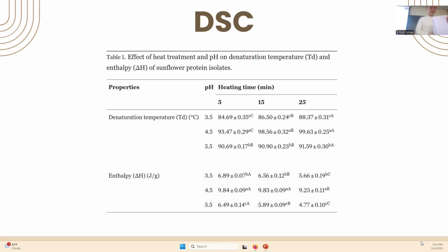Thermal stability was determined through DSC. Denaturation temperature indicates the thermal stability of proteins, and enthalpy indicates the extent of denaturation. From this table, we can see the higher denaturation temperature was observed at pH 5.5 as compared to that at pH 3.5. So it means the heat treatment increased the thermal stability of the protein.